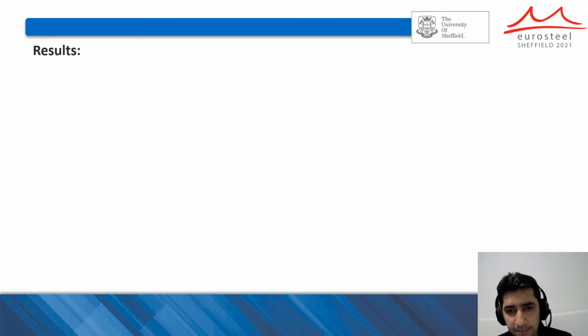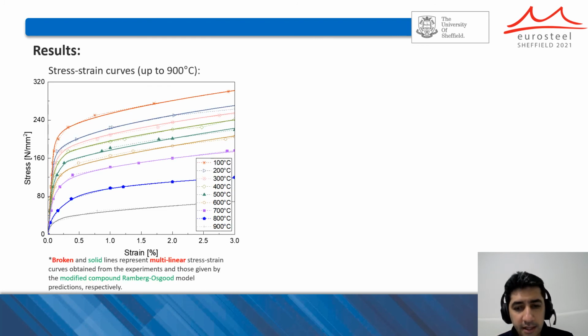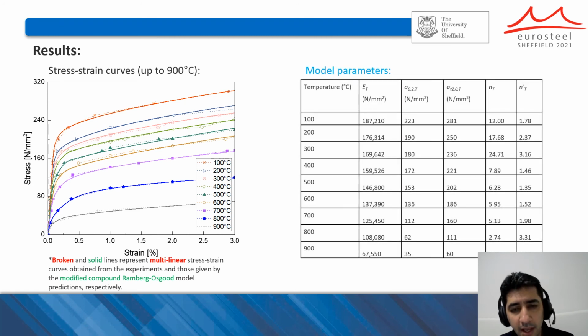In this diagram, you can see the multilinear stress strain curves with broken lines and the modified compound Ramberg-Osgood curves with solid lines at 9 different temperature levels up to 900 degrees Celsius. And the parameters of the model have been obtained and presented in the table.